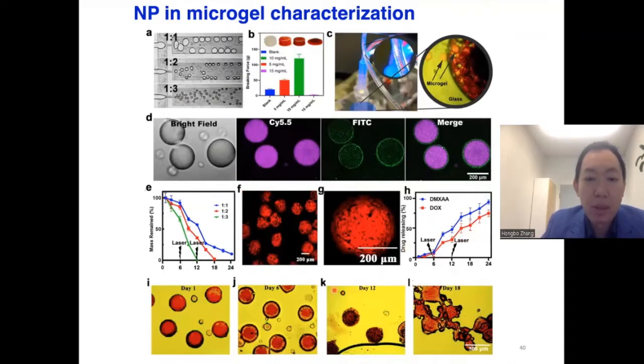And for this release, we can have a really sustained release because of this hydrogel matrix. In 24 days, we can still have some drug remaining. And you can promote the drug release by applying laser at different time points as you wish. For example, here we apply a laser at 6 days and 12 days, and at each laser point, you are stimulating this drug release.